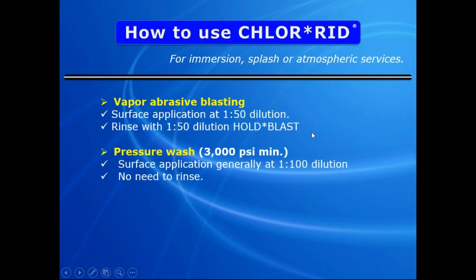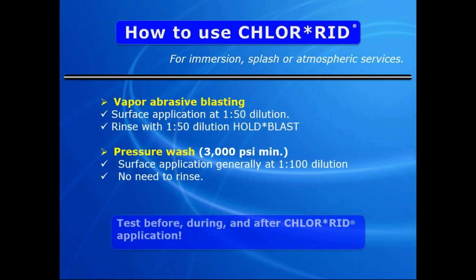You can use 3,000 PSI pressure washing, dilute at 1 to 100, and make sure that you cover every square inch, and you'll be able to get it clean. There's no need to rinse, and we do not recommend rinsing after use of CHLOR*RID, because most of the water in our industry today has about 35 to 45 parts per million of chlorides in the water itself. So if you come back and freshwater rinse after treatment, you just recontaminated your surface area. So just use the dilution rates that we recommend, and after it dries off, that's it, because the CHLOR*RID treats the salts and pulls them out of the steel. It's electrochemically attached. It pulls it out of the steel, and flushes it away with the water. It just flushes everything away, and now you have clean steel to work with.